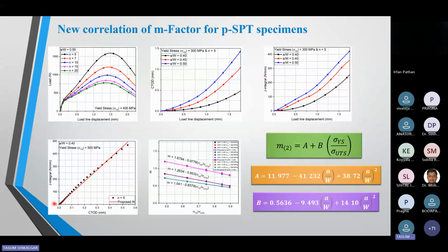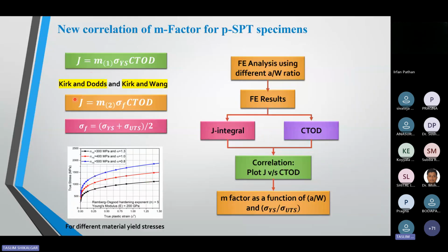So with the help of this, I proposed one correlation, that is M. How did I calculate M? I plotted this J versus CTOD. So M into sigma flow stress is the slope of the curve. And what is the flow stress? Flow stress is just the yield stress plus UTS divided by 2. And these correlations people are using for elastic plastic simulations. And if you are using linear simulations, people are using this correlation. This is the old relationship, and now Kirk and Dodds updated this correlation based on the flow stress.